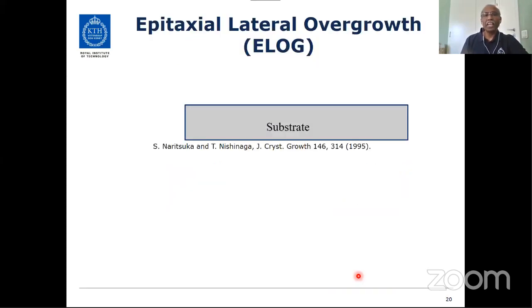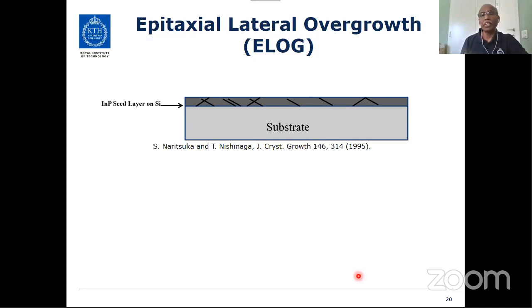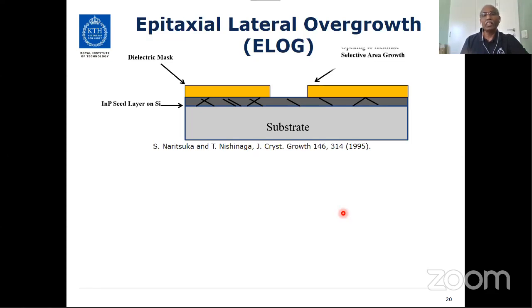So what is it? Actually, you have a silicon substrate, and you put some very bad quality indium phosphide on silicon. It contains a lot of defects. The lines are the defects. And then you put a dielectric mask, make an opening, and then you grow in the reactor. The layer will grow only selectively in the opening, and when it reaches the height of the brim of the mask, it will try to grow laterally. That is why it is called epitaxial lateral overgrowth.